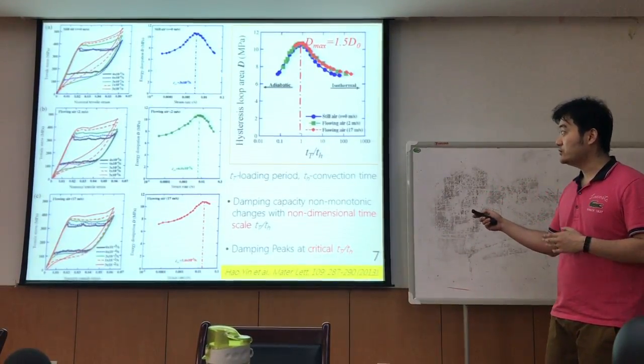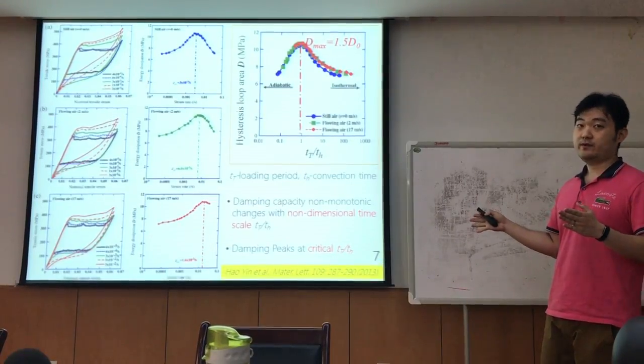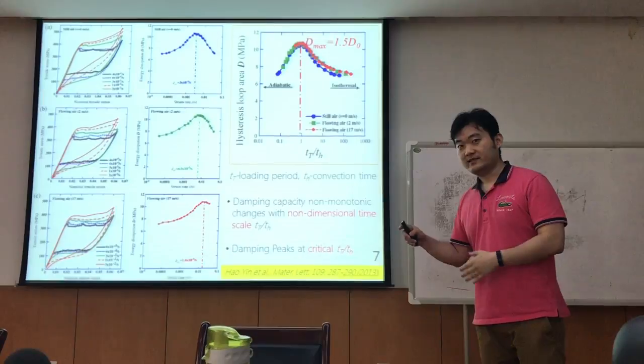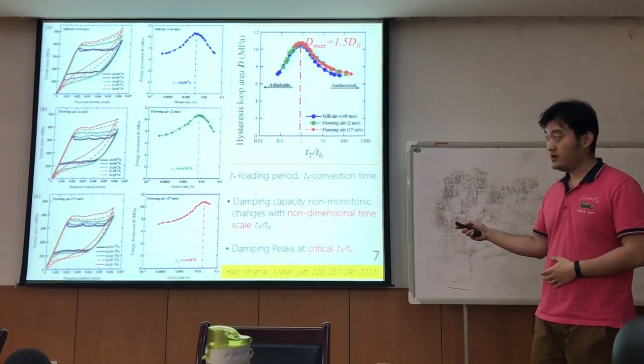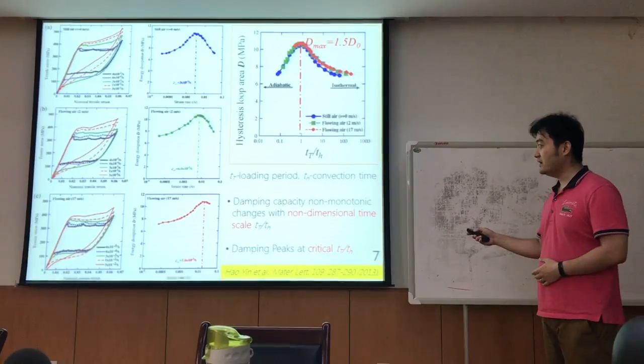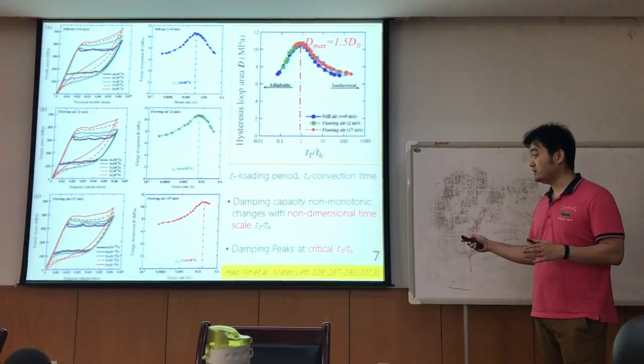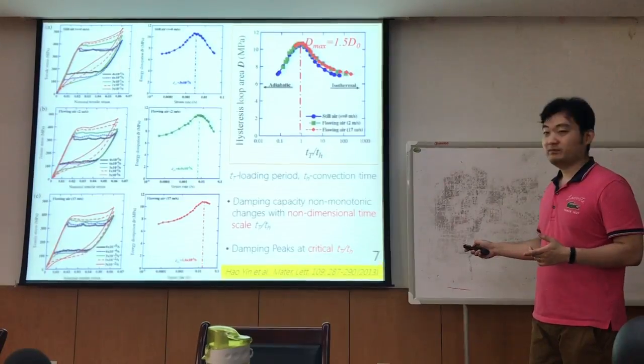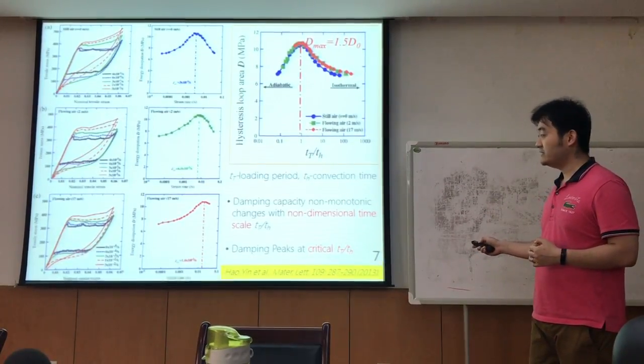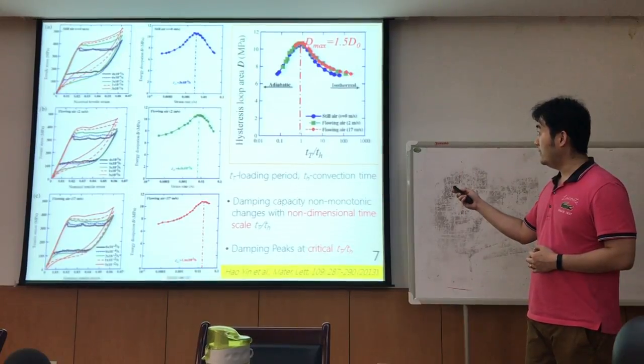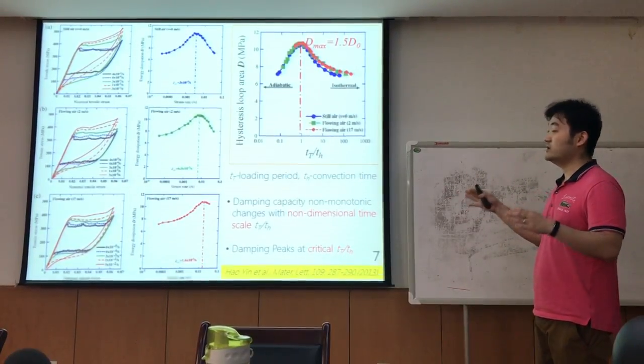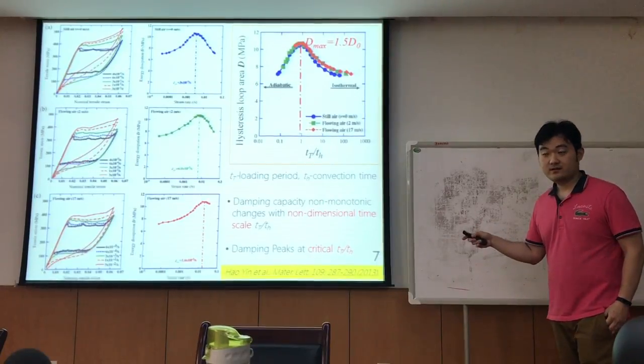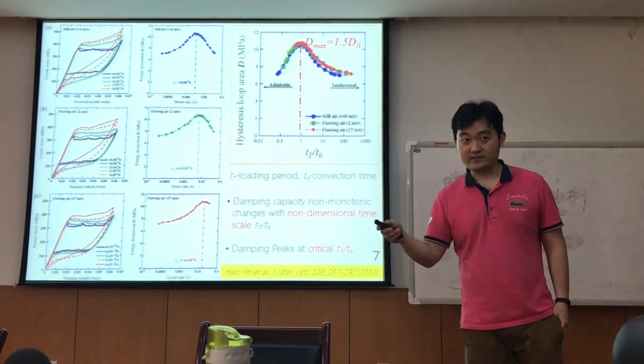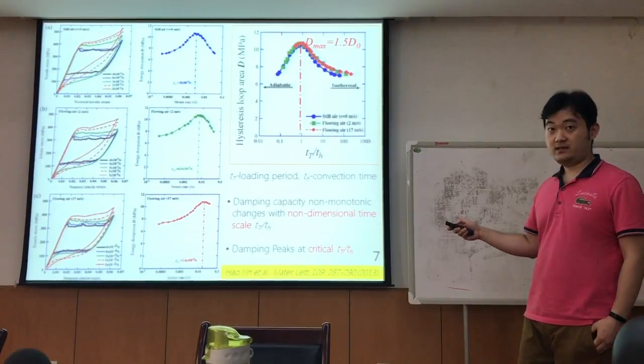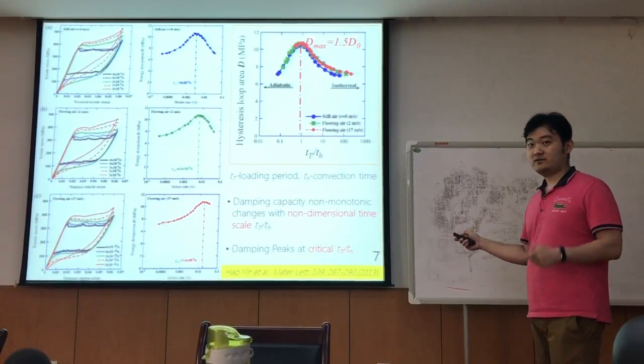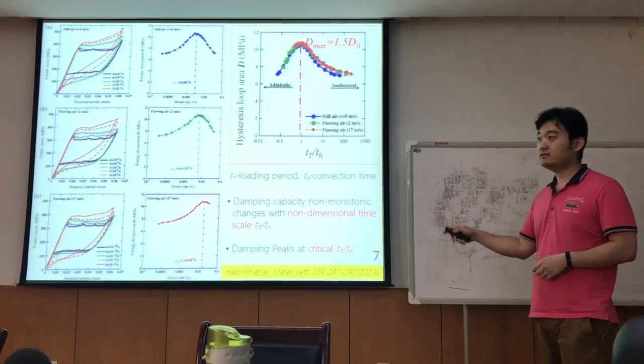This is not good for us to predict its hysteresis. But when we normalize the time axis, or the x-axis, by this non-dimensional time scale, Tt over Th, where Tt is the loading period, and Th is the convection time, we saw that all the curves overlap with each other. What this means is that the control parameter of the hysteresis, or the energy dissipation D, is this non-dimensional time scale. So we have these two conclusions.